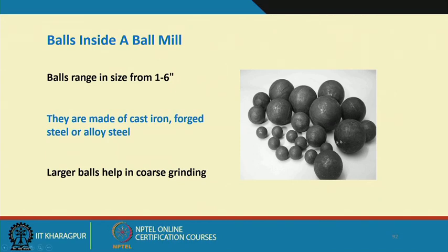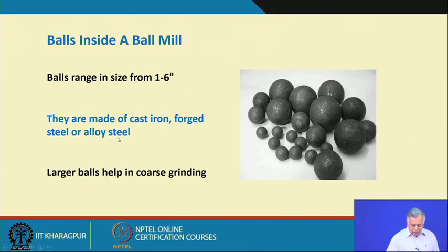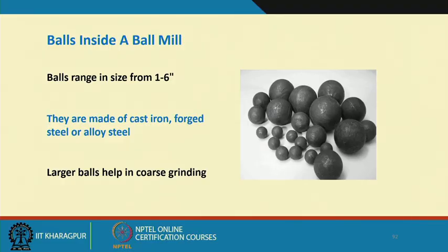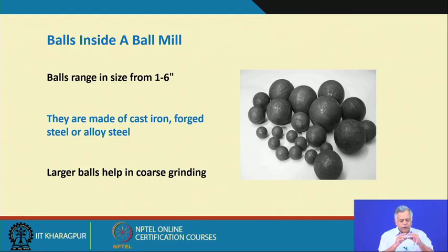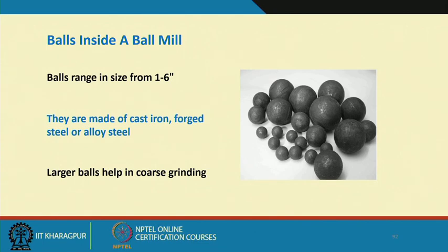These are snapshots of balls used in a ball mill — various sizes are shown. Balls range in size from 1 to 6 inches and are made of cast iron, steel, or alloy steel. Larger balls help in coarse grinding because the void spaces created between larger balls are much bigger. When only larger balls are used, particles sit in those large void spaces and are not ground further, generating a relatively coarser product. Using a mixture of smaller and larger balls fills those void spaces.